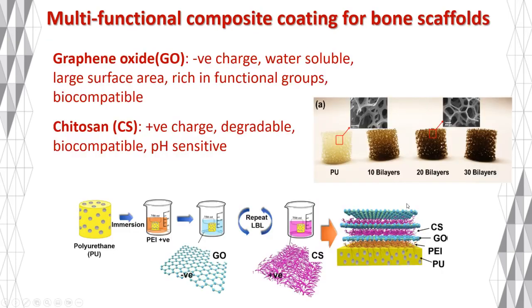So in this study, I utilized two materials that I previously worked with during my plasma research, that is graphene oxide and chitosan. The objective was to develop a novel composite coating for porous bone implants. And the concept behind this design is to create an implant system that can fill the bone defects, facilitate bone ingrowth into its porous structure. And additionally, the composite coating can offer multifunctions such as drug release, infection control, photothermal therapies, which would potentially target challenging bone diseases such as primary bone cancer or severe bacterial bone infections. To achieve this, we took advantage of the opposite charges of graphene oxide and chitosan and enabled a layer-by-layer self-assembly through the electrostatic attraction process to form a layer-by-layer hybrid coating structure on the surface of a porous scaffold.